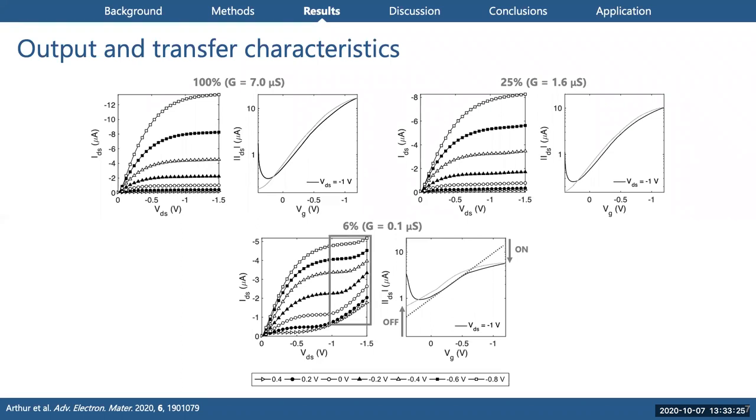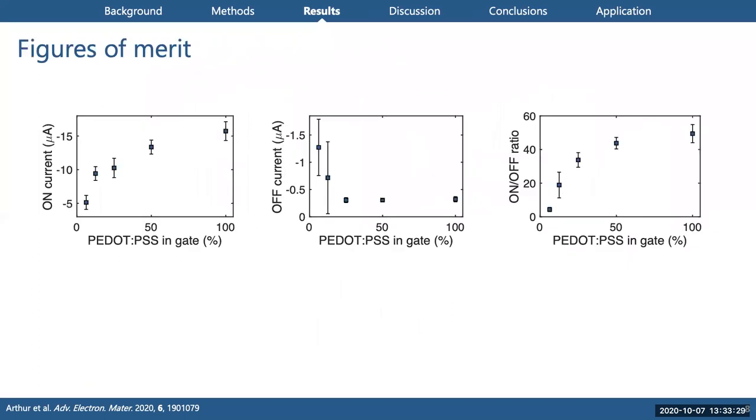This does suggest that we are seeing the same effect in both cases. Overall, as we reduce gate conductance, we see a few things. The on current or maximum current reduces, while the off or minimum current increases, indicating a reduced ability of the device to move ions in the moisturized PVP layer and thus a reduced ability to modulate the charge density in the P3HT channel.